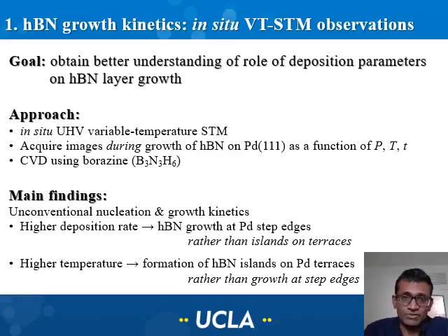We observe hexagonal boron nitride growth at palladium step edges under conditions that lead to higher deposition rates. This is unusual because conventionally, when thin films are grown epitaxially on a single crystal substrate, when you increase the deposition rate, one would expect to observe islanding rather than deposition at the step edges.